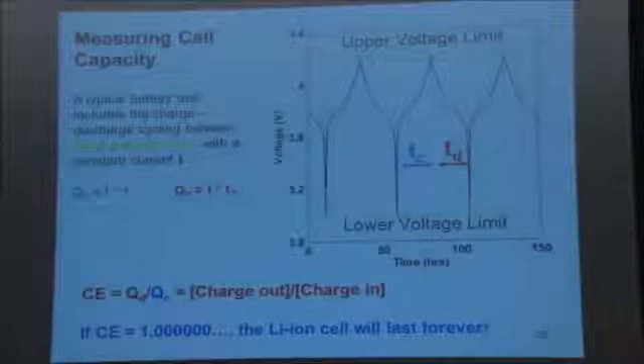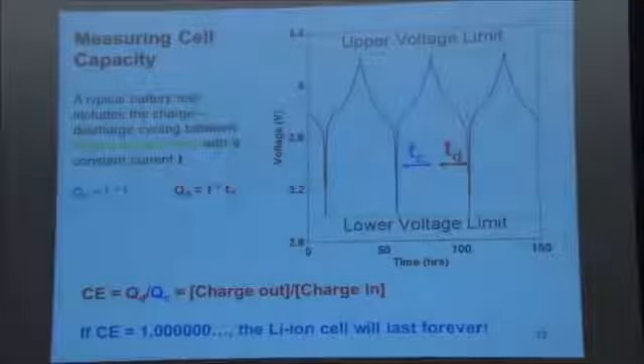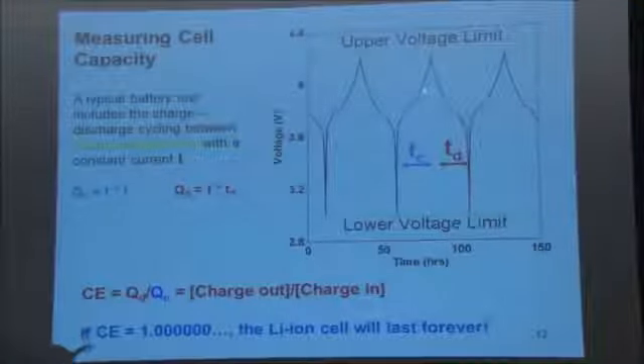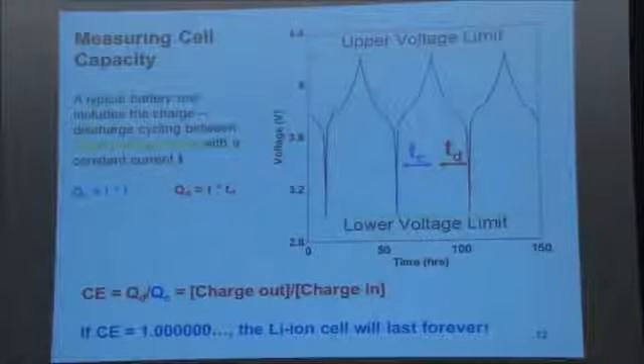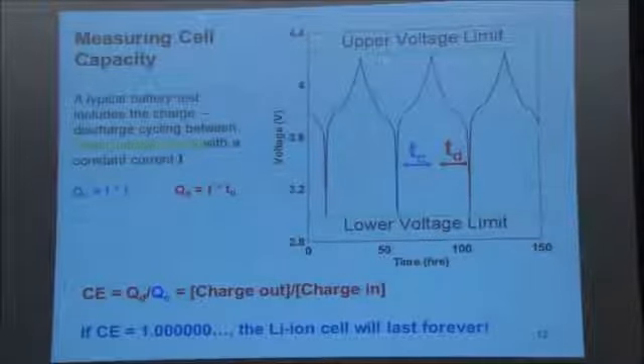So the capacity when you're doing this experiment at constant current is very easy to calculate. It's the constant current times the time of the charge for the charge cycle. That gives you the charging capacity. And the capacity in discharge is the current times the time of the discharge cycle. That gives you the discharge capacity.